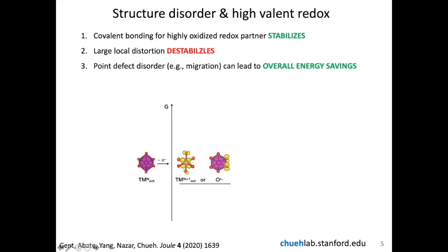So there are three things I want to talk about. These are the three contributions to the link between the stability and what I call the high-valent redox. So high-valent redox means accessing very high oxidation states, very deep delithiation, and very high voltage on the cathode. This is very desirable from an energy density perspective. And in the schematic I'm showing here, you can see the energy diagram. As I remove electrons from the system, you can remove electrons from the orbitals between the transition metal and oxygen, and the electrons can have various contributions from both the oxygen ligand and also the transition metal. And at first, this may seem to be the full story, but it's actually quite not the case.